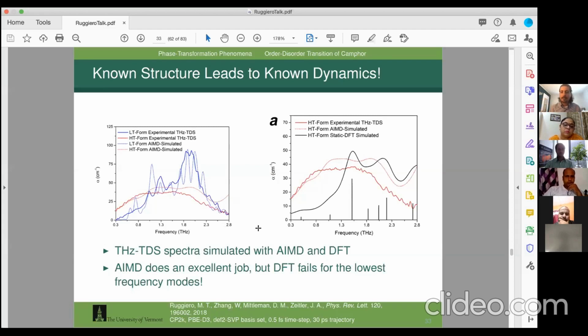What you see here is the experimental results in solid, and the molecular dynamics results in blue. We get good agreement for both the crystalline form, in blue, and the disordered form, in red.